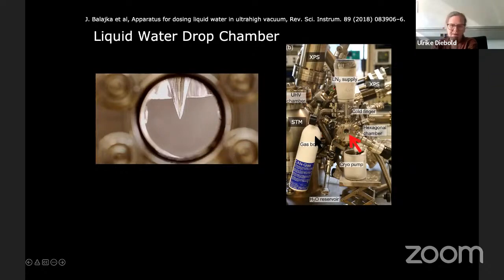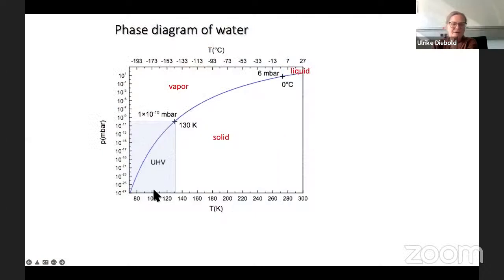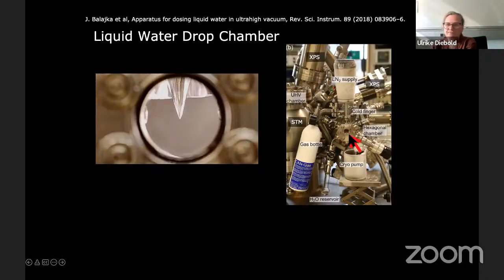So what we can do is, if you have water ice at low temperature, then the vapor pressure of water is very low, right? So here we pump this out. Here we have a little cryostat. This is the end tip of a little cryostat, at liquid nitrogen temperature. Then we can open one of these valves with a water reservoir and put in water vapor. In ultra high vacuum, we have vapor available. We put in the water vapor and form ice on this cryostat, and this little icicle is at low temperature, so the vapor pressure is low.